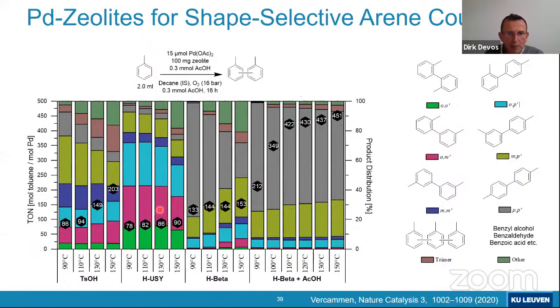We have worked a lot on this system, on this palladium beta, and actually the best performance is obtained if, together with the acetate, which is still in the zeolite because of the origin of the palladium precursor, the palladium acetate, you add some extra acetic acid. Then you really can get to very high turnover numbers, for instance, 400 molecules of toluene converted per palladium center, and that's even much higher than what you get with the homogeneous best system. And then of course you get the shape selectivity on top of that, because you see that now indeed the para-para isomer is produced in like 70–80% selectivity, pretty high selectivities, which is quite special if you consider that you could make the 6 isomers actually.